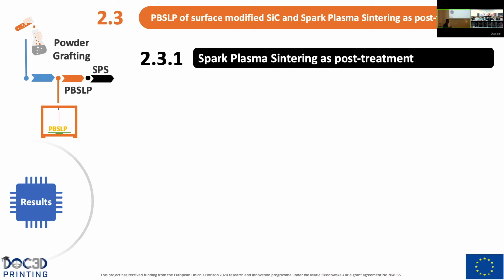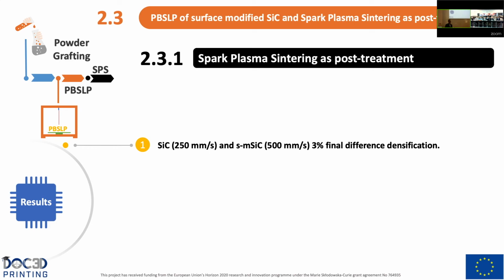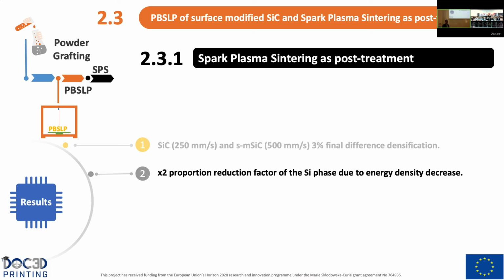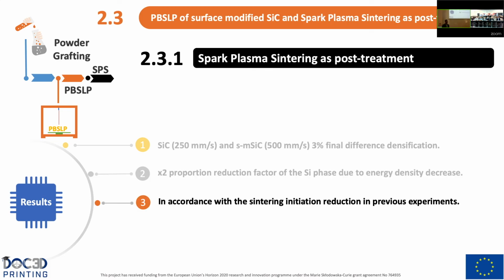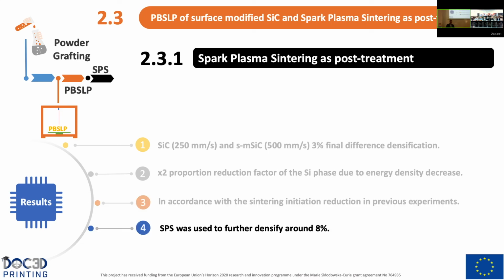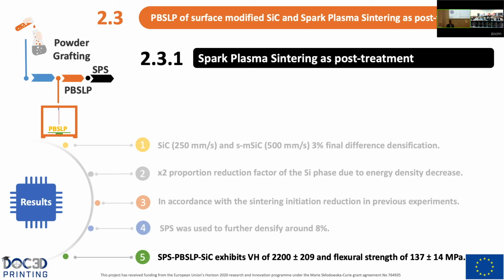So from this part, the results that we can obtain is that we have obtained silicon carbide and surface modified silicon carbide with powder bed selective laser processing with 3% final difference in densification. Next, we have observed a x2 reduction factor of the silicon phase due to energy density decrease. This is in accordance with the sintering initiation reduction that we have seen in previous experiments. We use spark plasma sintering to further densify the samples to around 8%. And finally, the silicon carbide, after additive manufacturing and post-treatment, exhibits a higher hardness of 2,200 and a flexural strength of 137 megapascals.